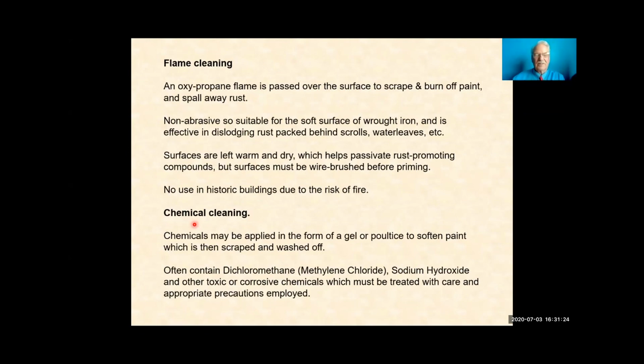The next process that I'd like to mention is chemical cleaning, which you can apply either as a gel or a poultice, or you can use a dip. It's often dichloromethane or sodium hydroxide, and these chemicals are not very friendly, so I don't recommend them, but they are very effective. We tend to use them only in the workshop or as a gel.